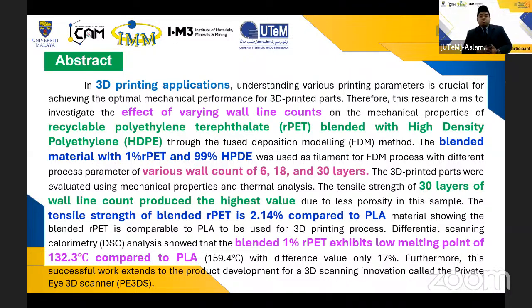Experimental results show that 30 layers of wall line count produce the highest value in tensile strength due to less porosity. It also shows that the tensile strength of blended rPET is 2% compared to the PLA material. Differential scanning calorimetry analysis shows that the blended rPET exhibits a low melting point compared to PLA.